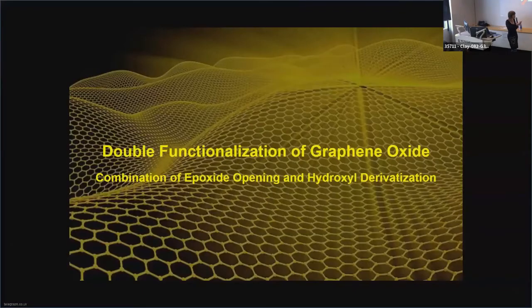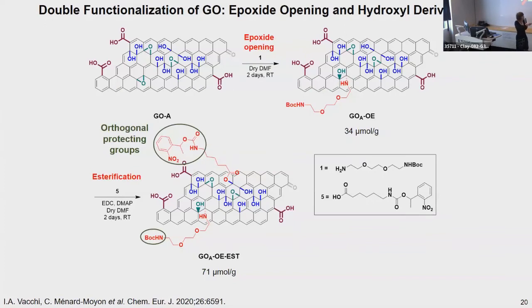So now that we have investigated the reactivity of the epoxides and the hydroxyls on graphene oxide, we then combined two different reactions to selectively functionalize graphene oxide and design strategies of double functionalization. And first, we combined the epoxide opening with this diamine derivative, as I mentioned before, with the esterification of the hydroxyls using this carboxylic acid derivative linked to this amine protected, in this case, with a photo-cleavable protecting group, which is orthogonal to the Boc group